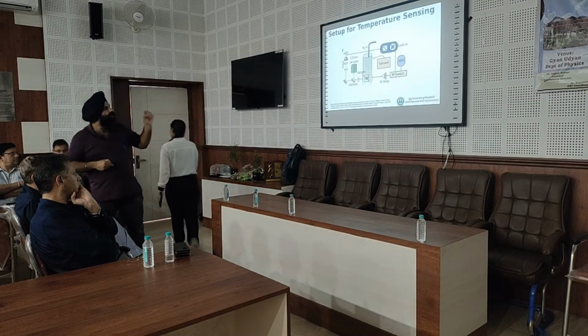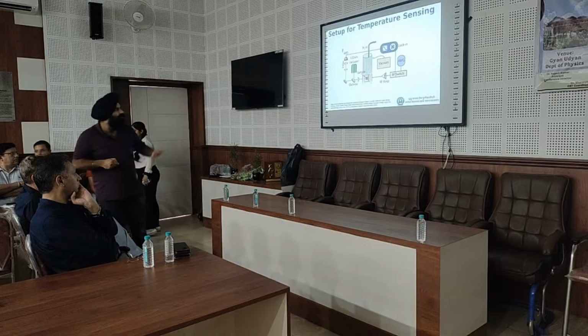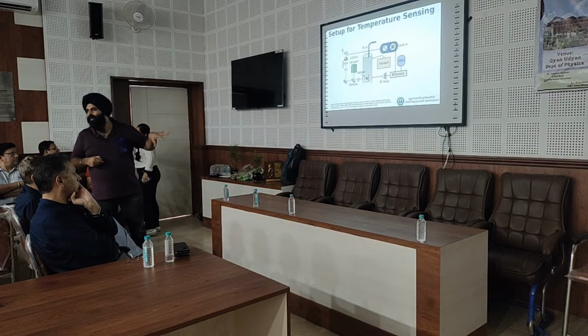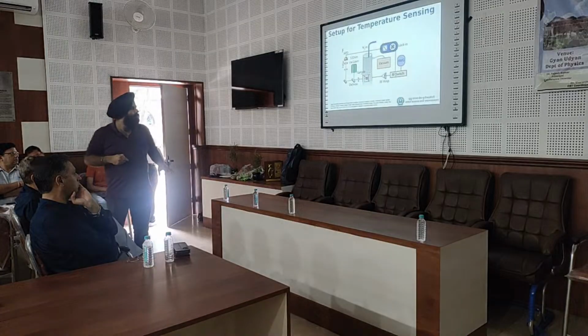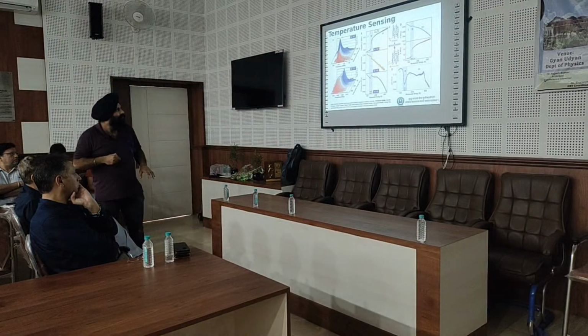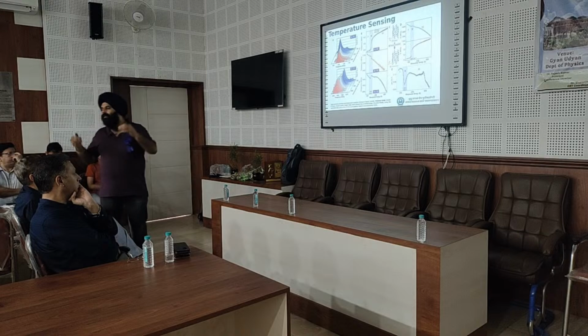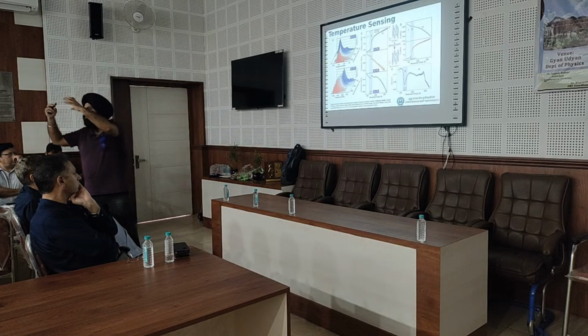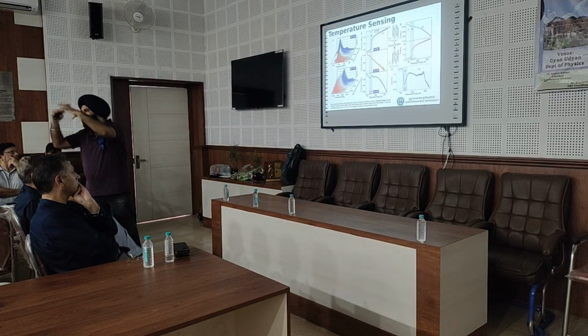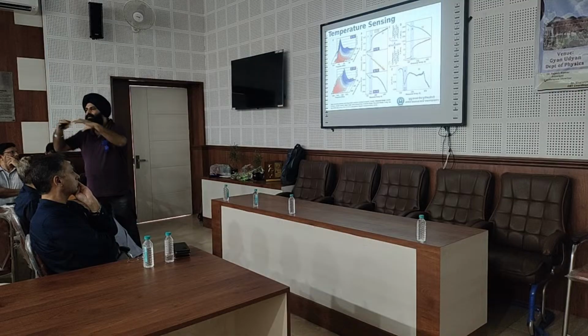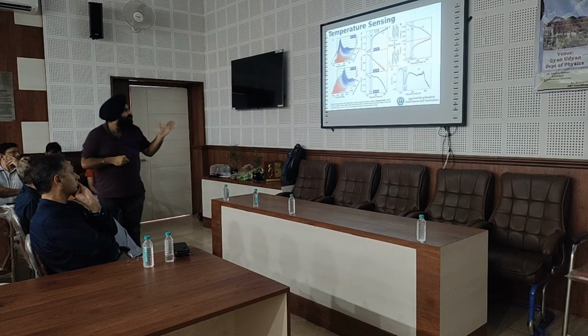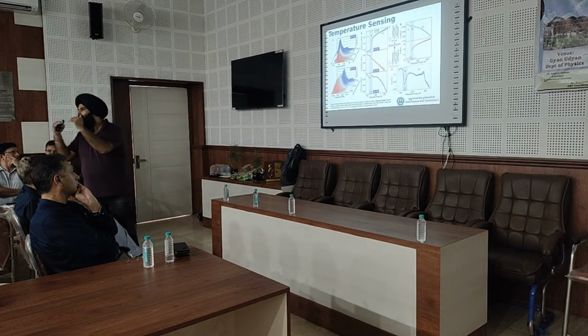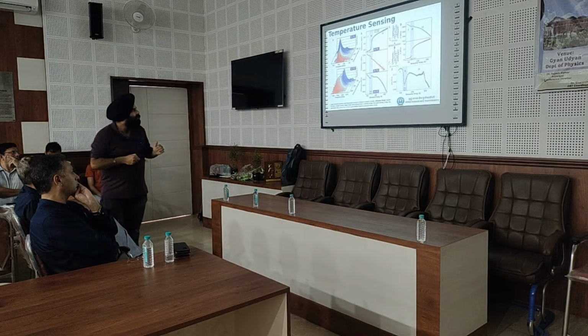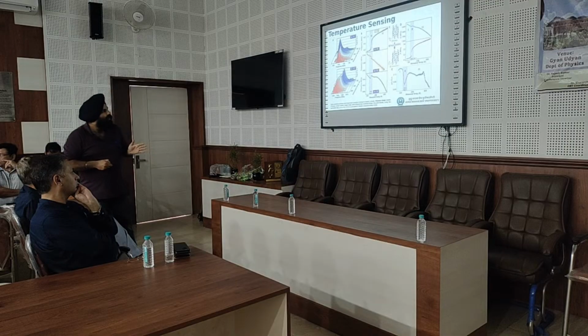Later, I used the same organic crystal for measuring temperature. So this is the cryostat. The setup is modified, and then I change the temperature. When you change the temperature, the peaks start getting shifted. The idea is that in an organic crystal, when we change the temperature, the lattice strain changes, the environment changes, the magnetic field around the pentacene changes, and due to that this ODMR peak gets shifted. Because the zero field splitting changes, and this change is tracked with the temperature. For example, for the XZ transition, you can see this kind of thing.